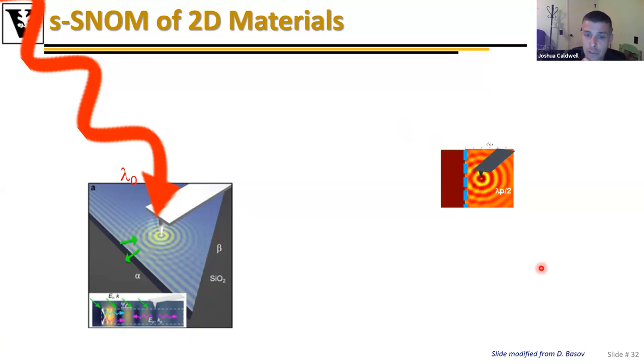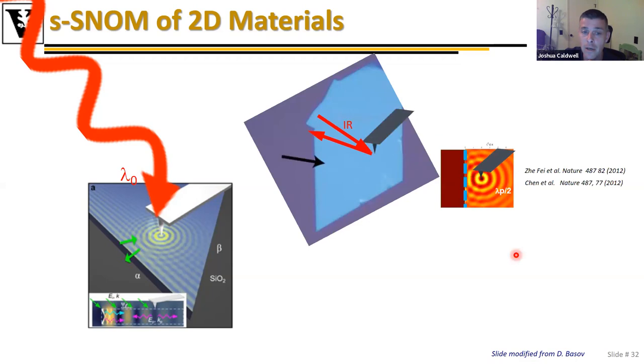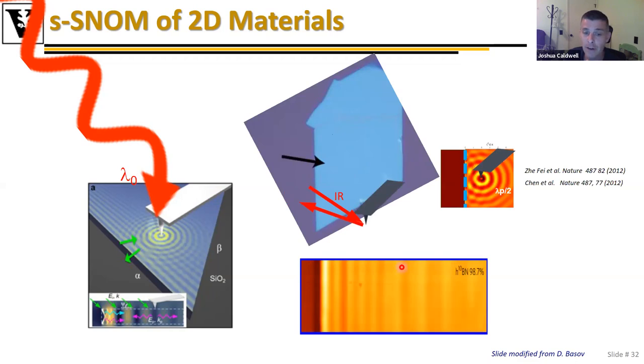Now, if I introduce some kind of reflective edge, for instance, the edge of a flake, or a defect or a fold in the material, I can get that to scatter back. And the interference between the outgoing and returning polariton modes results in this interference pattern, which I can then use, by scanning across the whole structure or a whole flake here, to identify the periodicity of these modes. By looking at the distance between any two fringes, I can figure out the overall wavelength, convert that to momentum, and now plot out the dispersion.